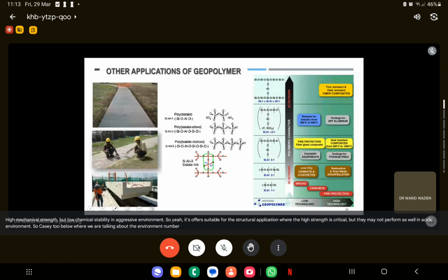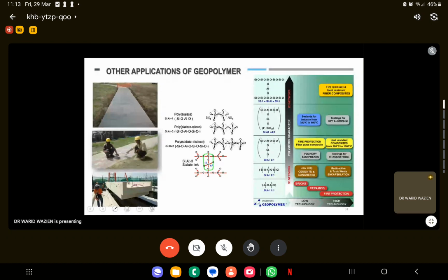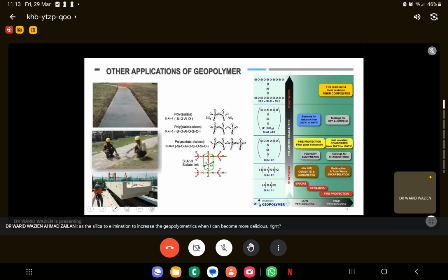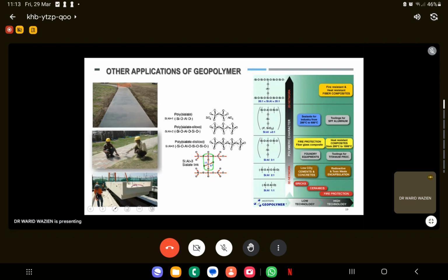Alright. As the silica to alumina ratio increases, the geopolymer matrix pun akan become more siliceous, right? This typically will improve the chemical resistance and durability, making this material ideal for the application in aggressive chemical environment. For example, waste encapsulation, chemical containment, and lining of the sewers and pipes that might be exposed to acidic or corrosive substances.